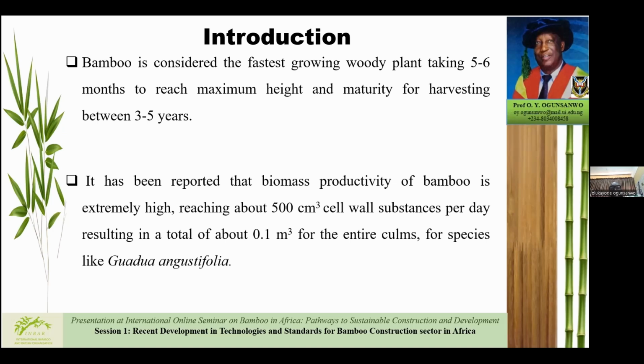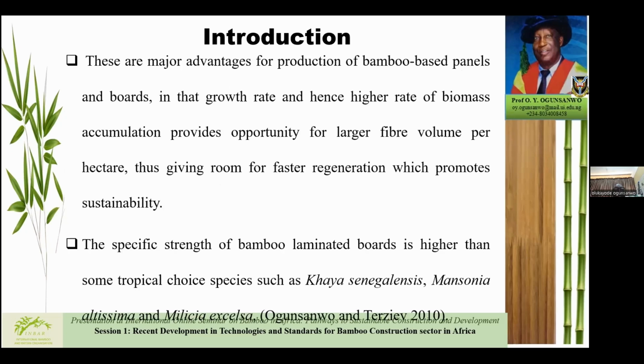So bamboo itself is considered as the fastest growing woody plant. That is, it takes about 5 to 6 months to reach mature height. And then the maturity of bamboo is between 3 to 5 years, a little bit more than 5 years in some cases. And then it has also been reported that the biomass productivity of bamboo is extremely high, reaching about 500 cubic centimeters in terms of their cell wall substances per day, resulting in a total of about 0.1 cubic meter for the entire culm for such species like Guadua angustifolia.